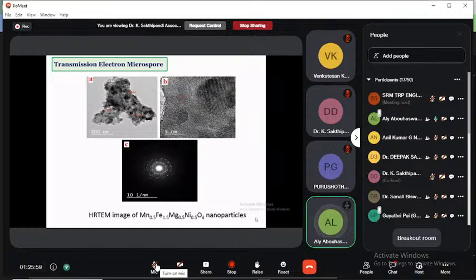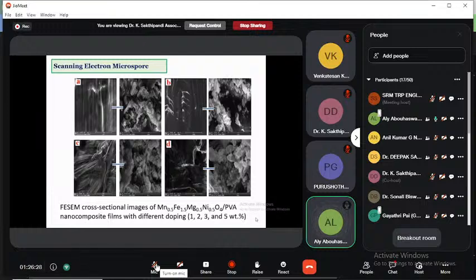Yes, this is the transmission electron microscopy of our spinel ferrite. From this figure, we can confirm the preparation of spinel ferrite in nanostructure with crystal size about 25 nanometer. And after that, we see the scanning electron microscope.